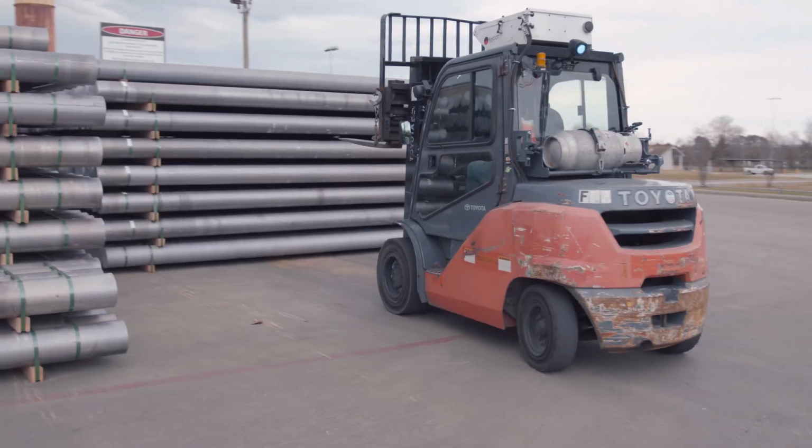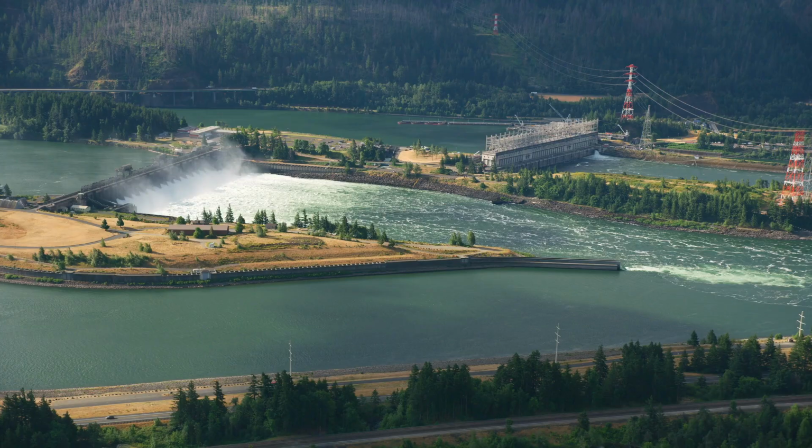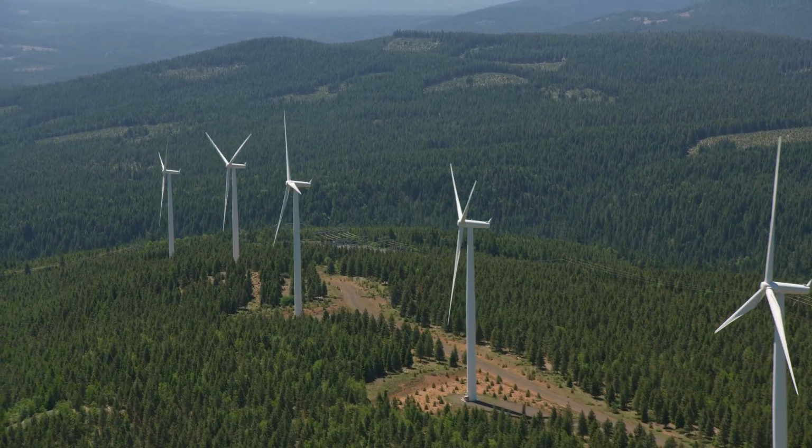So there is no industry standard to define low carbon aluminum at this point. For primary aluminum production, typically aluminum produced with a clean energy source, or hydroelectric-sourced smelters, is considered low carbon aluminum. So they would be around 4 to 5 ton of carbon per ton of aluminum.